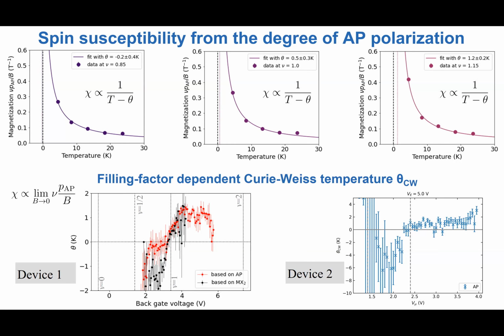And the picture there is this. Again, it's a hand-wavy argument, but at very low filling factors, you have these isolated electrons in these deep Moire sites. These are like uncorrelated quantum dots. And when you find a way to flip the spin of an electron to a higher energy state, and these energy level spacings are very, very small, then the relaxation can take seconds. That's calculated in quantum dots, the T1 time of an electron spin. This can be seconds long. So even if, let's say, 1 out of 1,000 excitons ends up flipping the electron spin, a very weak process, it can have a long lasting effect. So that's, of course, a limitation, a strong limitation.